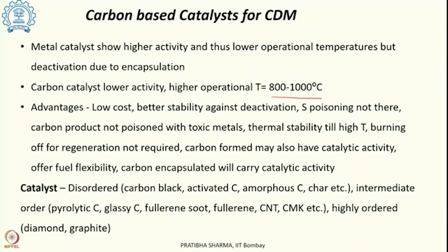The cost of these carbon catalysts is lower, and they have better stability towards deactivation. Unlike the metal catalyst, sulfur poisoning, or poisoning from certain impurities present in the feedstock, is not there, or it is resistant towards sulfur poisoning.